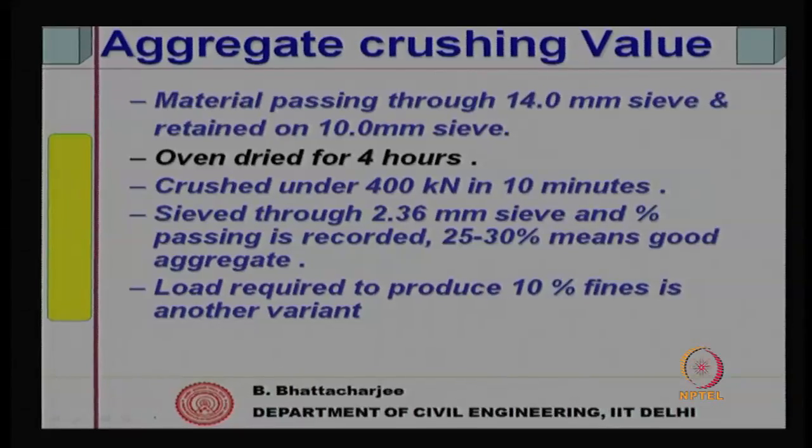to measure relatively, to compare two aggregates relatively, and also to specify. It is used in specification. That means you specify that the aggregate crushing value, which is expressed as a percentage, should not be more than 32 or something like that for use in structural concrete and so on. So, in relative comparison, the one having a lower crushing value is better compared to the one having a higher crushing value.